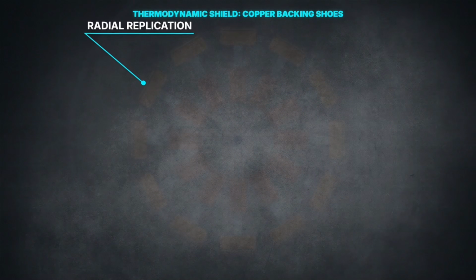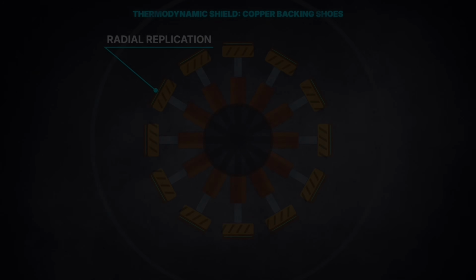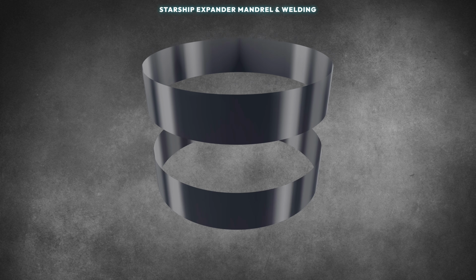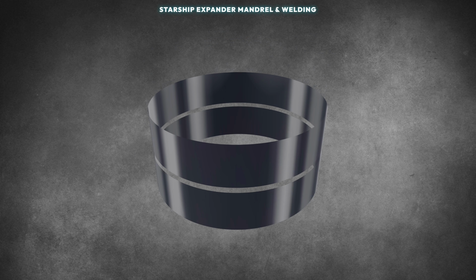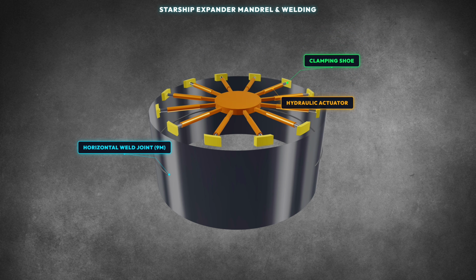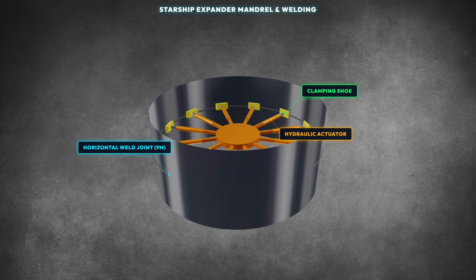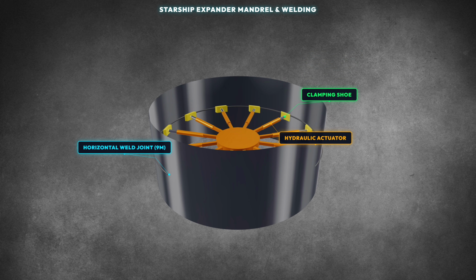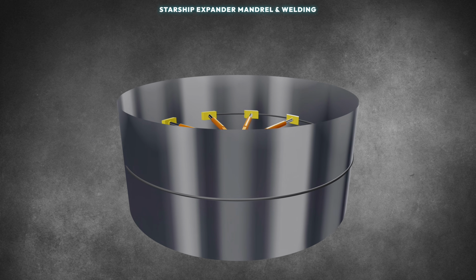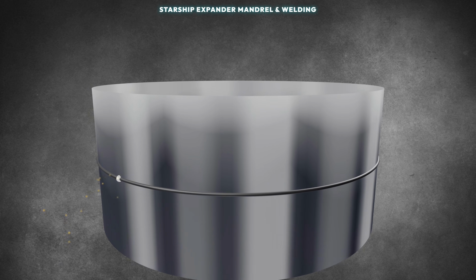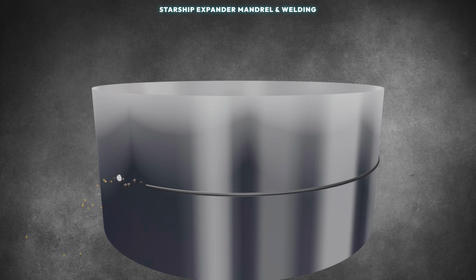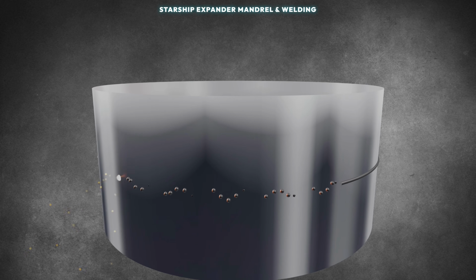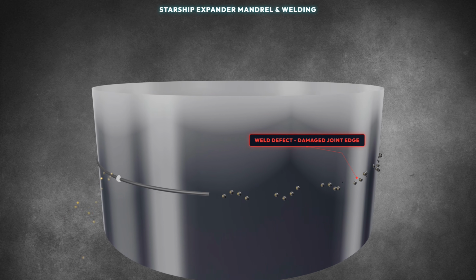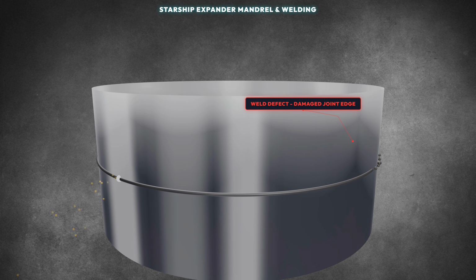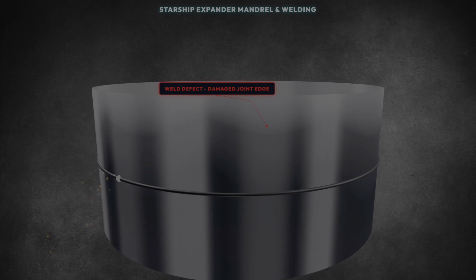Yet, cooling the metal is only part of the solution. The robot must still guide the laser along the seam with perfect accuracy. Even with the mandrel locked, micro vibrations and minor ring imperfections cause the joint line to drift. A path deviation of just 0.1 millimeters is enough to miss the keyhole tunnel, resulting in a weak weld. At 3 meters per minute, manual corrections are impossible.